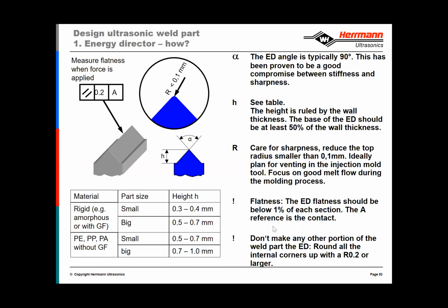A question that often comes up is how large should the energy director be? Typically, there are two recommended angles for energy directors, and we'll only talk about the typical 90-degree. This is the proven angle that we will recommend to our customers more often than not. But depending on size constraints, wall thicknesses, those kind of things, we may see a 60-degree angle at some point as well. And that's okay. You just may have to make the energy director a little bit taller if the angle can't be achieved at 90 degrees.